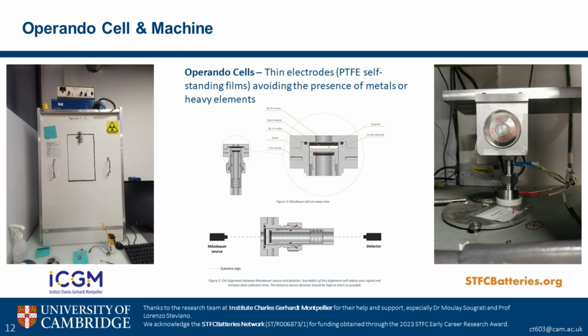The difference being that you have beryllium windows to let the gamma rays through, and you wouldn't want to use heavy metal current collectors because they would also block the gamma rays. So you would tend to use PTFE self-standing films. And then the battery sits on top of the source and underneath the detector. And you can cycle it there while the spectra are collecting.